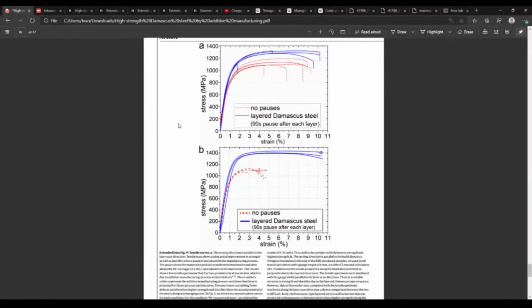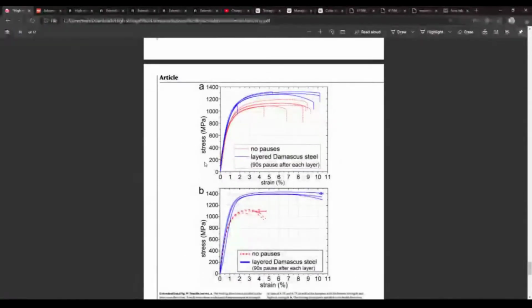Here's the graph. They show the strain testing. This is tested by pulling the material apart. They say the outlier here is caused by defects in the manufacturing processes, and that's very common. It's the problem with additive manufacturing of metals, because there are always voids, little bubbles of air, empty space that sometimes cause failures.